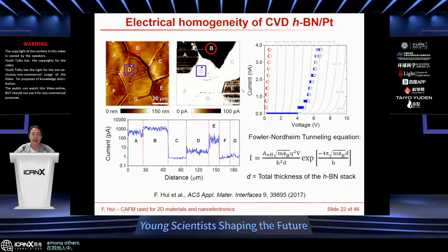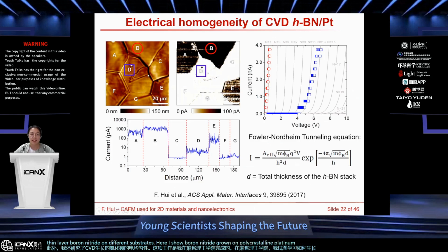among others. In addition, I also studied the electrical homogeneity of CVD-grown boron nitride. This work I have done at MIT, where I tried to learn how to grow thin layer boron nitride on different substrates. Here I show boron nitride grown on a polycrystalline platinum substrate. I collected the topographic and the current maps at the same time, and when we take a cross section line across these grains, we see the current varies among the grains, but within the same grain, it is more homogeneous.